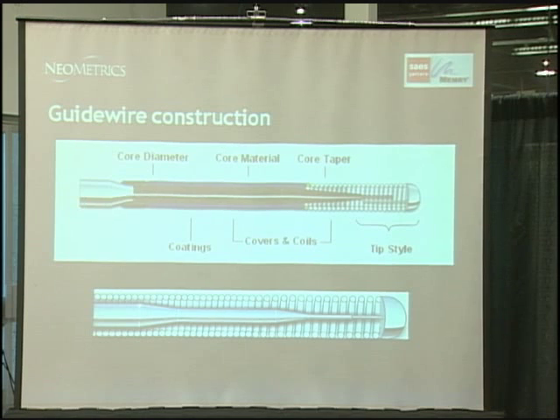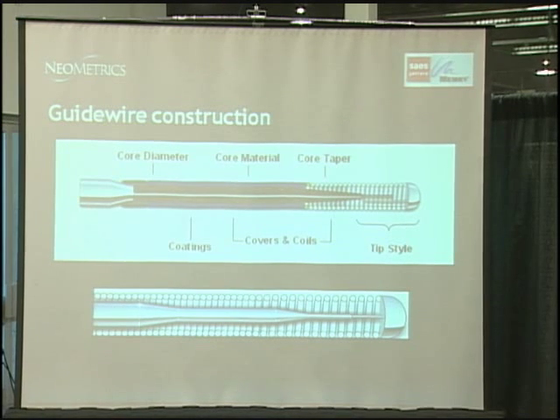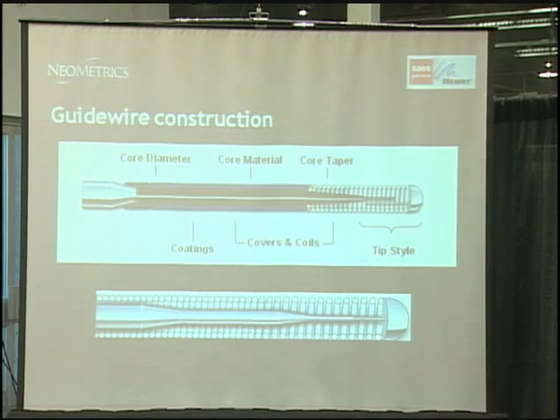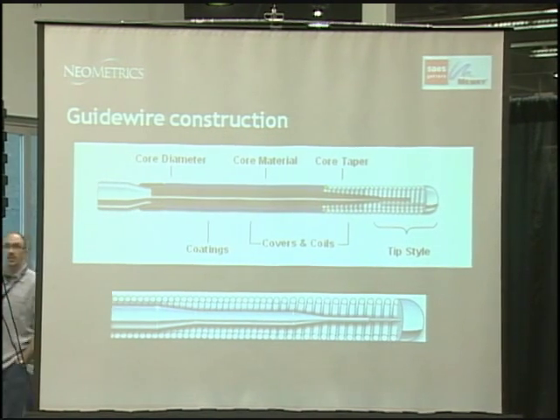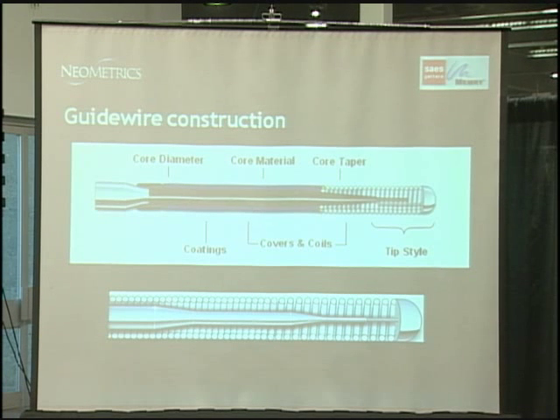Basic guidewire construction 101, and many of you in the audience here probably know about this. There are an infinite variety of guidewires, but one category of design would be what you see here, which is a solid core guidewire, an attenuation or a tapering of the tip done by centerless grinding, much as the Royal Masters and the Glebar machines can do here. A distal tip which has a radiopaque coil on it or some radiopaque material. In some cases, a safety wire or a very, very fine diameter distal tip for navigational purposes. And then over the top of that, potentially radiopaque polymers or primer layers, tie layers for the application of hydrophilic coatings and other slippery distal tip coatings.